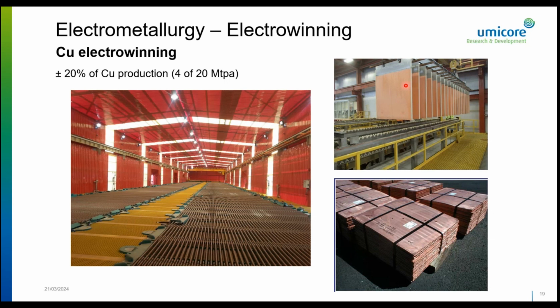Here you can see how these cathodes look. You have what we call the blank. It's a stainless steel plate, and on top of it there's a copper layer deposited. So it's a copper plate deposited on the blank. These can be removed from the blank by what we call a stripping machine. They flex the cathode, and the copper plates fall off and are packed, as you can see here. The blanks, after they're stripped, are put back into the cell, and you start the process again. This usually takes about 7 days to produce a copper plate in this way.